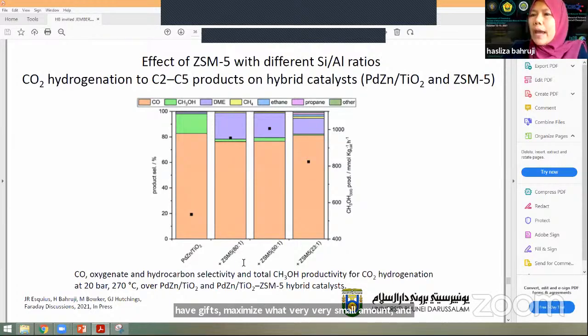And when we added ZSM5 at an 80:1 silica to alumina ratio, this is when we started to see methanol being reduced, but we started to produce a lot of DME, and we also reduced the selectivity towards carbon monoxide. When we have silica to alumina 50, we see basically a similar observation, but when we reduce further to 23, I'm starting to see this kind of product, which is a mixture of propane, ethane, and other hydrocarbon products.